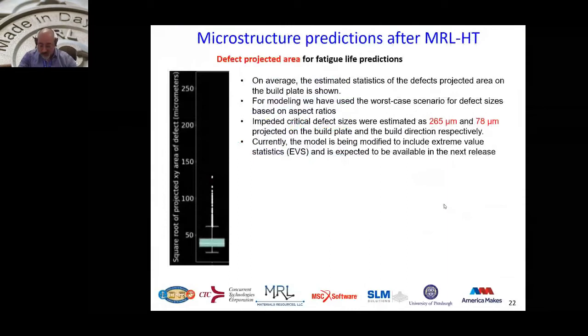When it comes to looking at the predictions of the defects, this is the trickiest one that we are looking at in the material, where we are using a machine learning tool to predict the box plot. So what you're looking at in the bottom left corner is the measured box plot, and we have predictions of box plots as well, which is the statistical information about the defects that feed into the fatigue model through extreme value statistics.